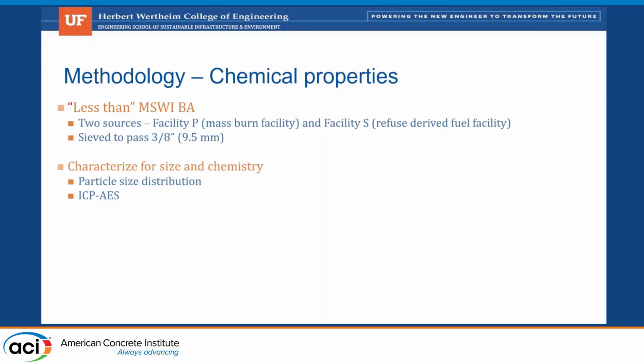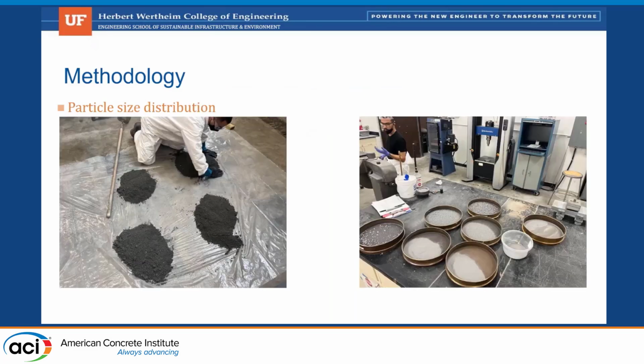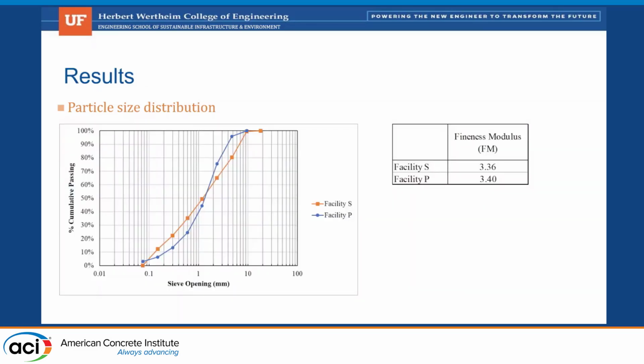And so we did some particle size distribution, we did some ICP. Particle size distribution was a little bit on the crude side. We did some sieves, and then we went ahead and pulverized that. When we look at our average size, we see that we're looking at a D50 of around a millimeter. And more than 50% of that bottom ash is greater than that.